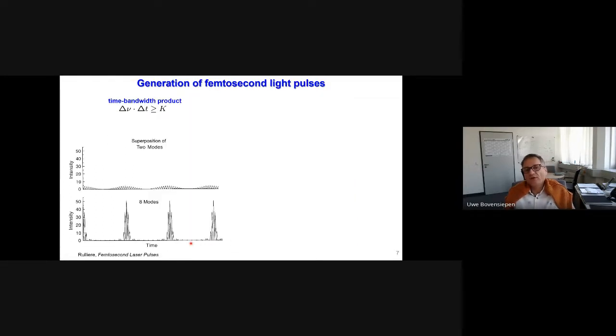Now, how do we generate these femtosecond light pulses? This is a very simple principle that I would like to mention here. This is simply going back to the superposition of modes. I show you here the superposition of two modes. This is something you all know. There is this beating occurring. Now simply take more than 2 modes, for example, 8 modes. And you see already with these 8 modes, you have a piling up of intensity at well-defined times and a loss of intensity in between.